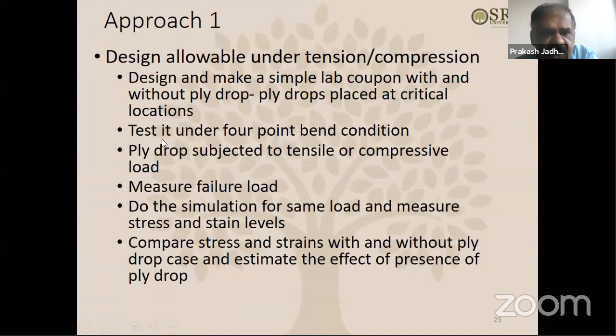Going back to this, we will be using four-point bend conditions, and the ply drops are subjected to tensile or compressive load by placing them near the tensile surface or the compressive surface, and then we measure the failure load. After that, you do the simulation for the same load, same boundary conditions and same coupons, measure the stresses and strains, and compare them with and without the ply drop case, and estimate the effect of the presence of the ply drop.